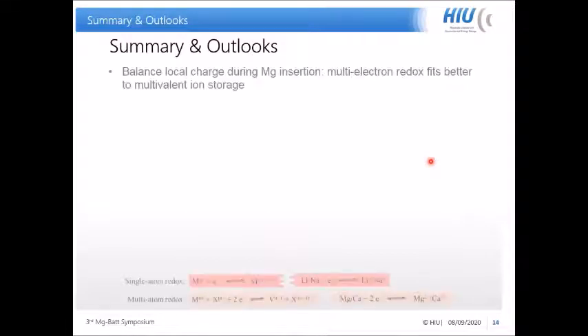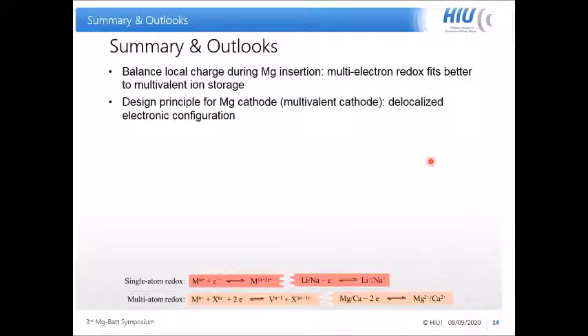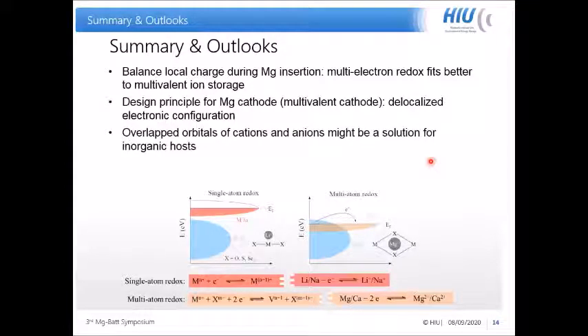To sum up, first of all, we have proposed to consider the local charge balancing during magnesium insertion. In this regard, we believe that multi-electron redox might fit better to multivalent ion storage, and this could also be a design principle for magnesium cathodes or even other multivalent cathodes. And as we presented before, a cathode with delocalized electronic structure will be more promising for ion mobility.